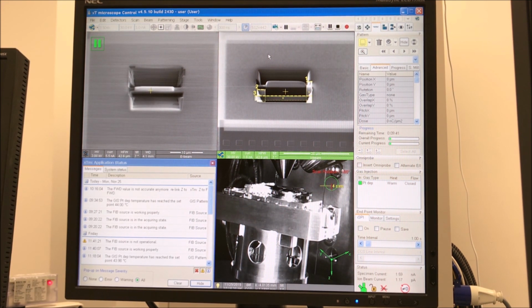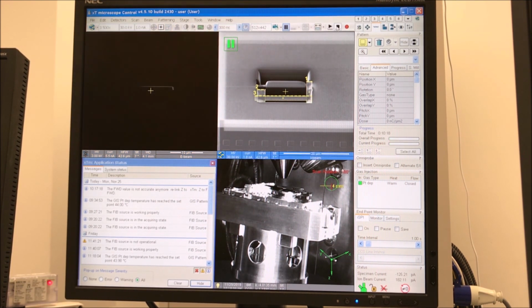And so the idea now is you're cutting around the lamella and you're leaving only a really small part attached to the actual substrate or the bulk. And so it's really pretty easy to see when you've cut through your defined areas using the live ion beam signal from the area that you're milling. Again, you may need to manually adjust your contrast and brightness to see it better.